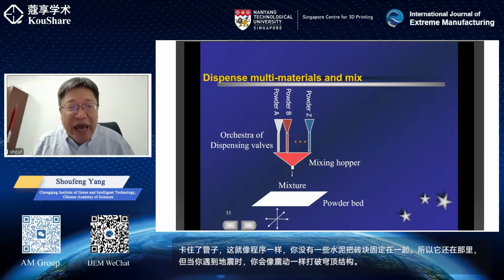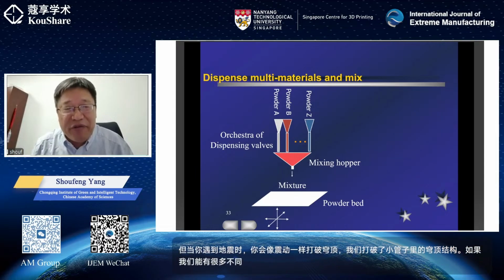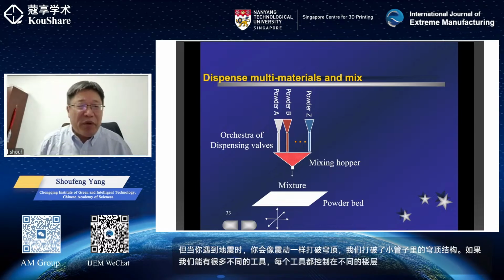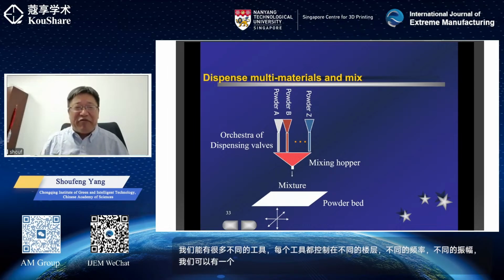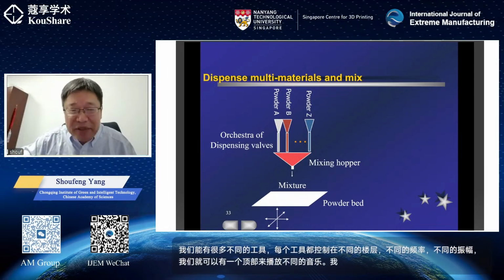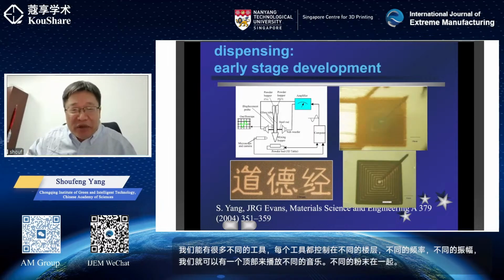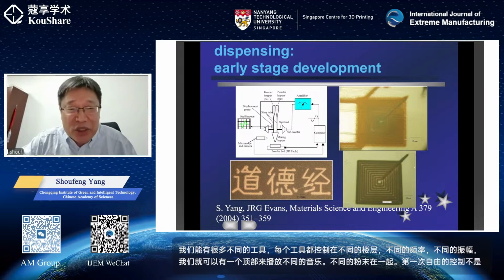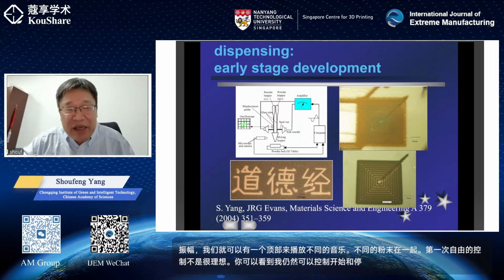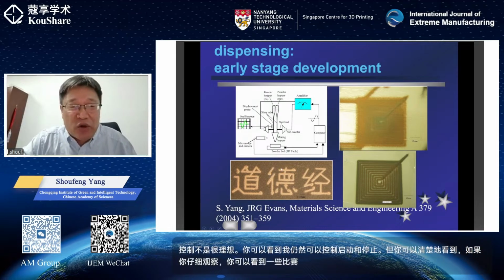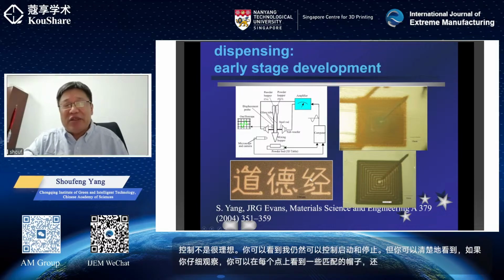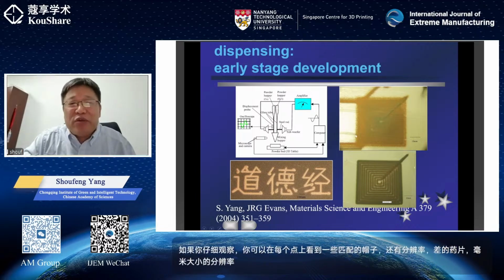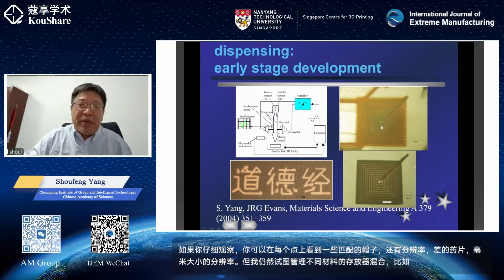And if we can have a lot of different tubes, each controlled at different flow rate, different frequency, different amplitude, we can have an orchestra to all play different music. We can even mix all these different powders together. At the first time, the control is not very ideal. You can see I still can control the start and the stop, but if you see closely, you see some match heads at each dot, and the resolution typically is millimeter size. But I still managed to deposit a mixing of different materials like copper and steel by online mixing.